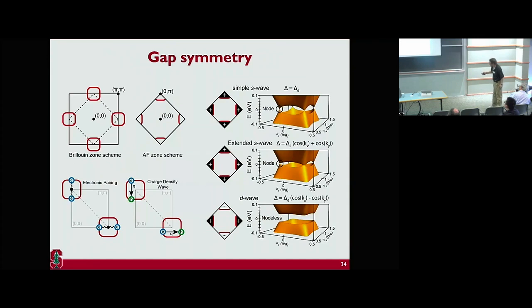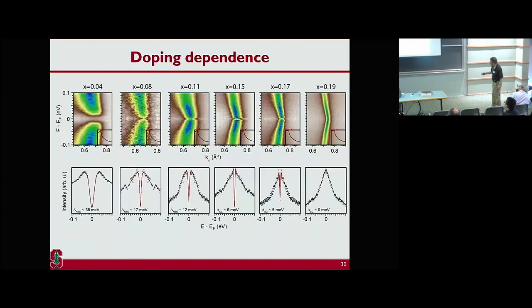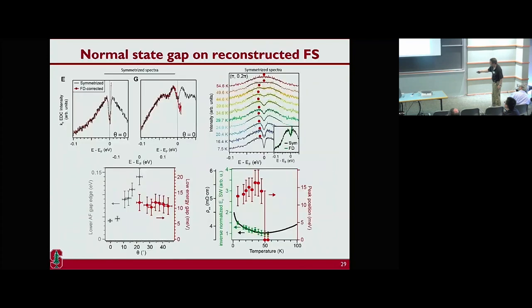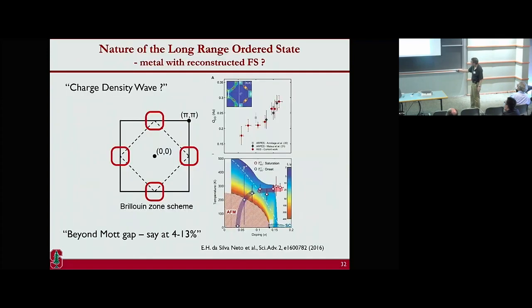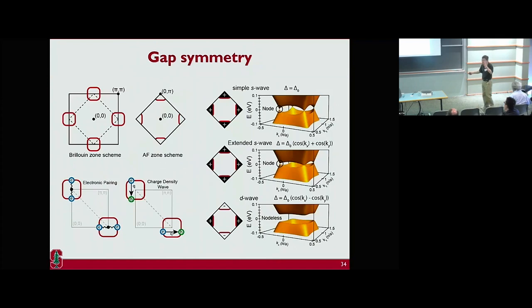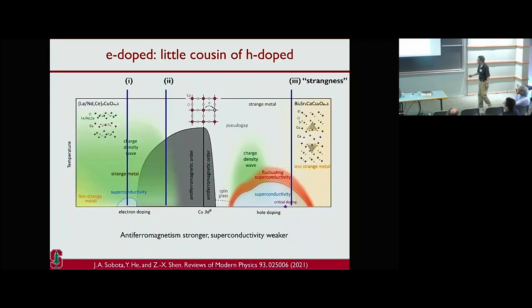Again, Donghai has done this calculation and looked at various systems. I should say one more thing. This gap is constant along that piece of Fermi surface, doping and angular independent. And he showed that, contrary to what was certainly early believed, D wave should have a constant gap. If you have any sort of S wave, you will end up with a node. In this case, it's consistent.